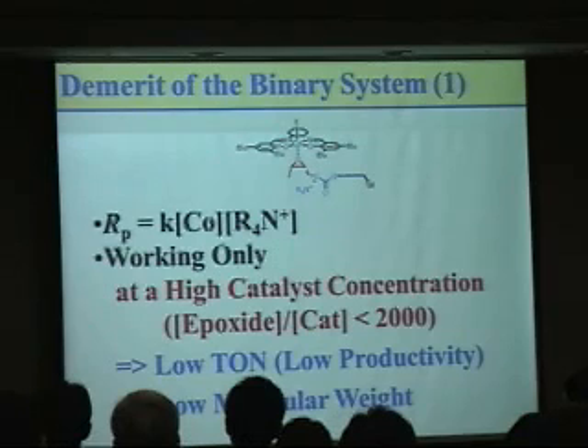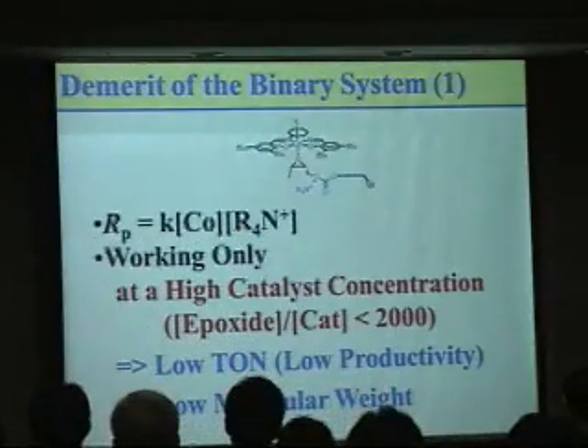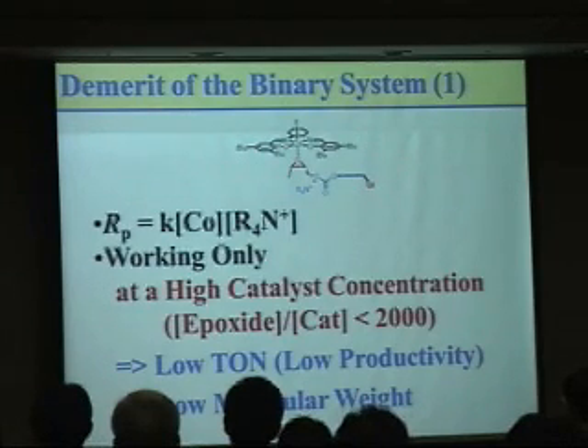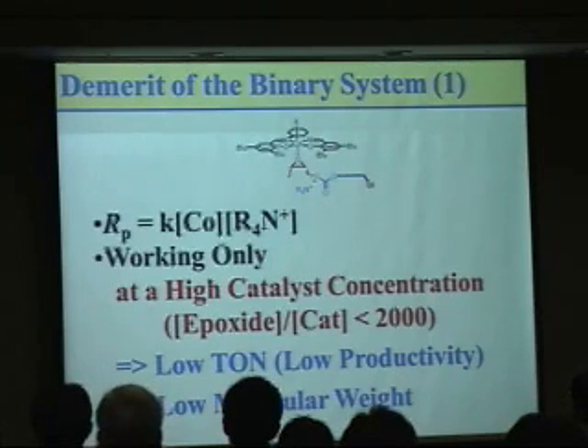When we added a very small amount of catalyst, there is little chance for the two components to meet each other. So the catalytic activity was realized at a high catalyst loading, with an epoxide to catalyst ratio below 2000. So under this condition, the highest attainable turnover number is limited by this number, so we cannot get a high turnover number up to 100,000 or something like that under this condition.